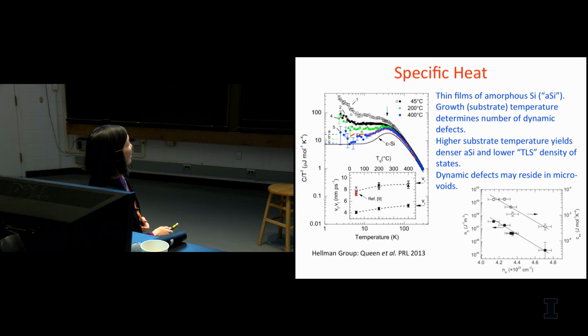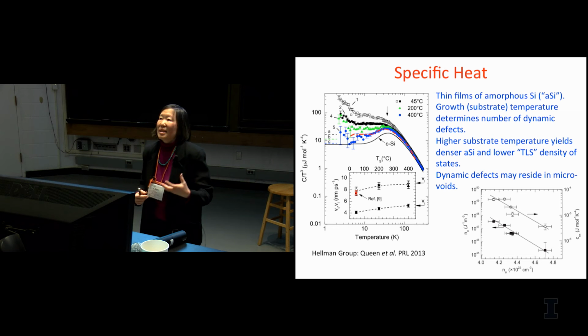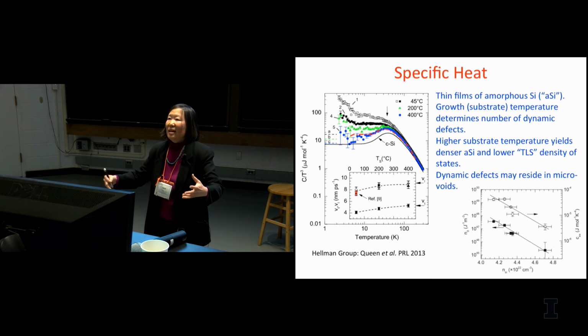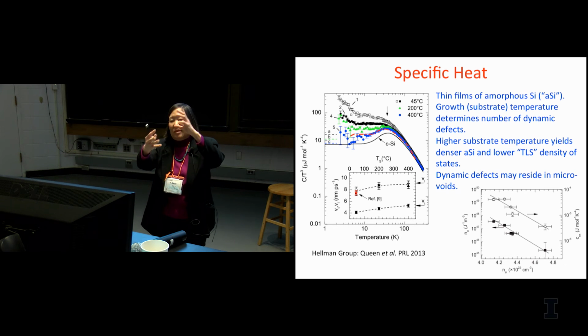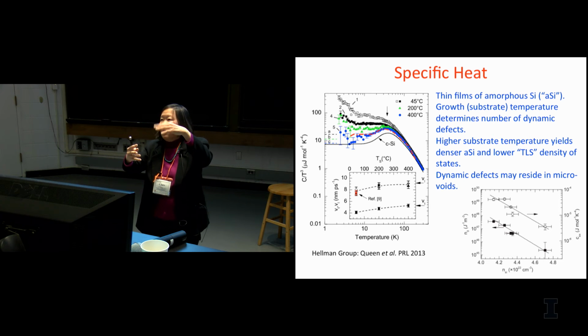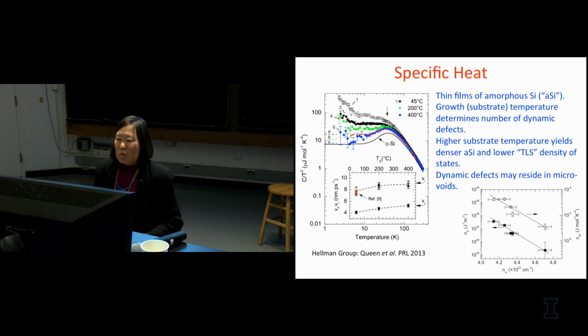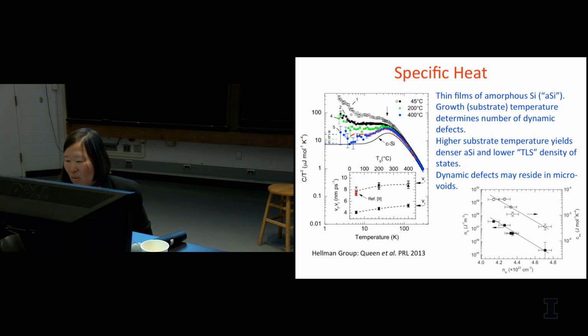So here's the density of the silicon film versus the defect two-level system density of states. And you can see that as you increase the density of the film, you get fewer and fewer of these low energy defects. So they speculate maybe these defects reside in some kind of void, right? You have a lower density, you've got a little bit extra room, you maybe have some little cavity, you maybe have a defect or something, atoms wiggling around on the walls of that void.